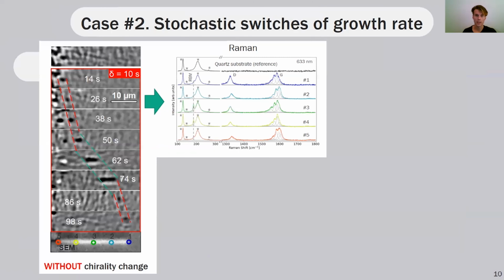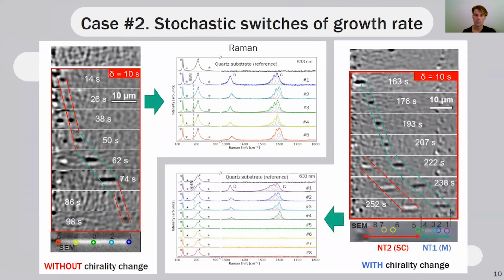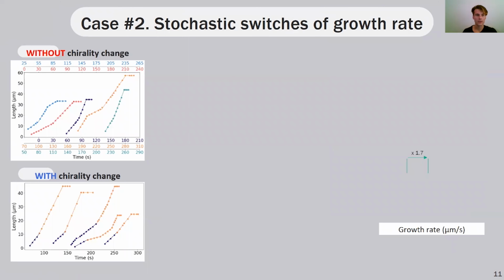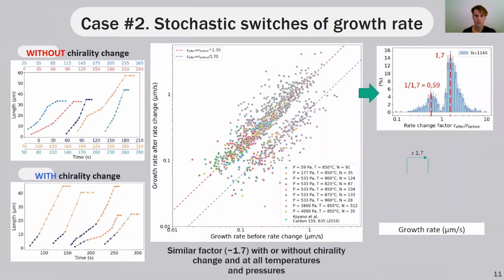Another case we evidenced is the stochastic switches of growth rate without change of chirality and with change of chirality, based on comparison of video, of Raman features along the tube, and of SEM. Here you can see the kinetic curves of both of these cases. You can see that both with and without chirality change, switches between growth rates are abrupt, from one constant growth rate to another one. We tried to search for correlation between growth rate before and after change of chirality. And we found a similarity factor of about 1.7 for both increase of growth rate and decrease of growth rate.